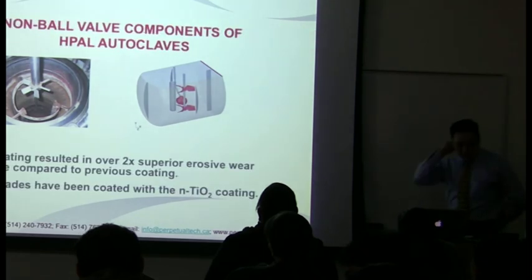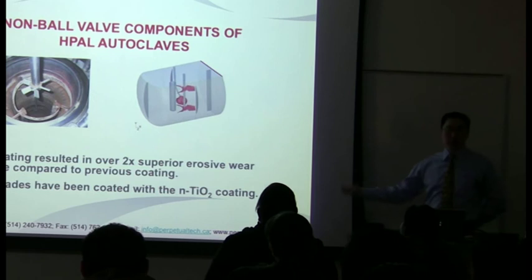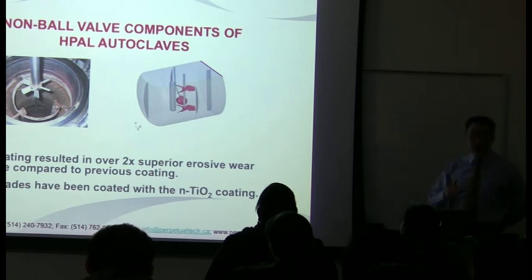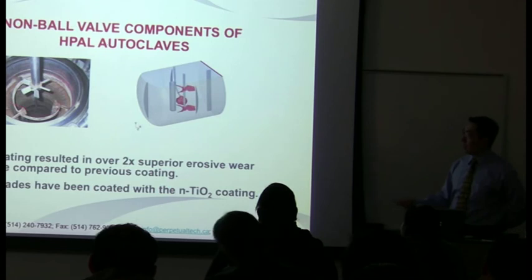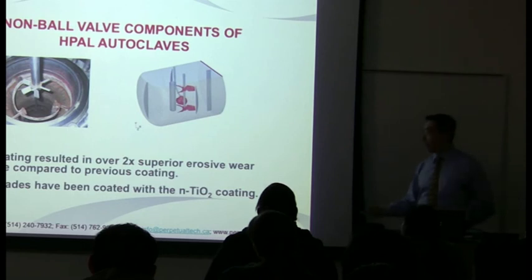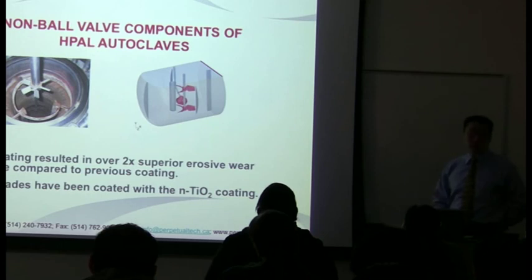Now, someone at Murrin, a mine in Western Australia, thought, okay, well, if it's doing well in that application, how well will it do in erosion, pure erosion application? So these are impeller blades or stirring blades. This is their lab scale setup. Nano-TiO2 coatings were applied onto these blades, and they carried out their standard test. And the response from them was that the nano-TiO2 resulted in over 2 times better erosion wear resistance compared to what they were using before.